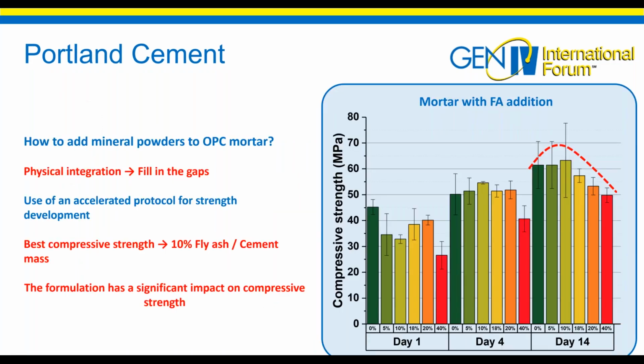The integration of mineral additive into a Portland cement mortar can be done in different ways. I will present the simple addition case to you. It consists of simply adding the mineral additive to a given formulation. This integration highlights a maximum percentage with high mechanical performance in compression. In this case, 60 MPa at 14 days with 10% of fly ash addition. But why does this performance decrease over 10% of fly ash?